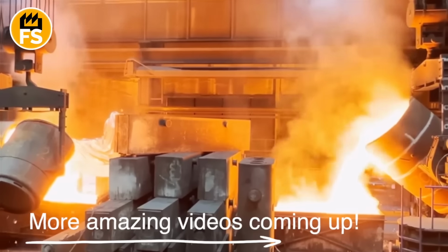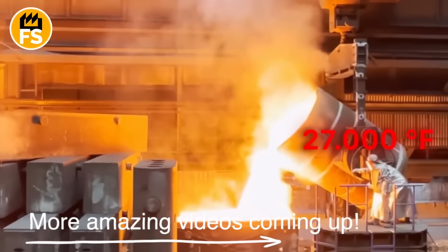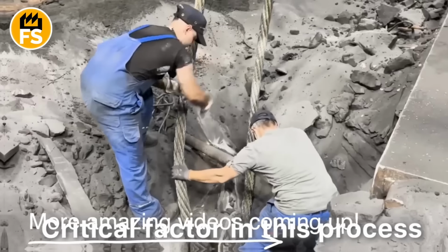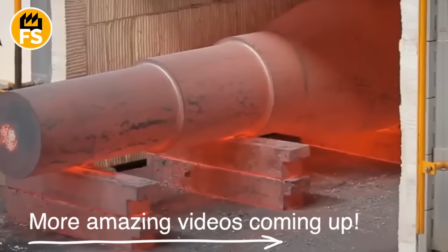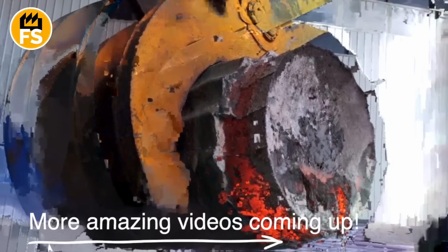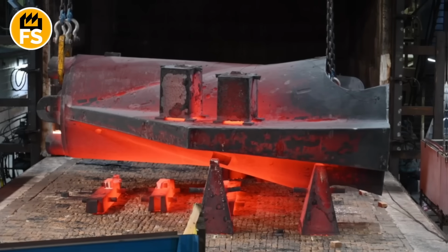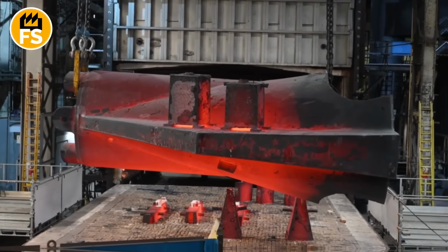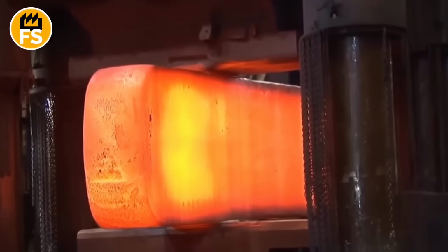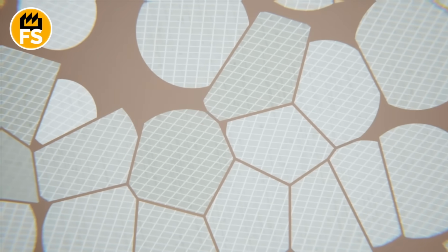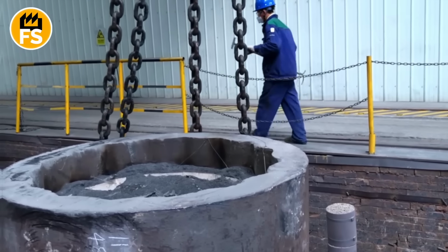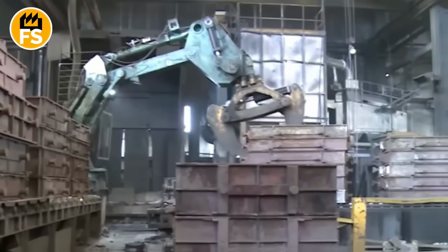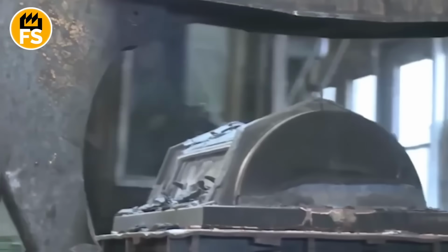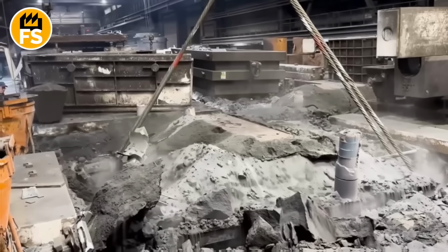Immediately after pouring the molten metal, which can exceed 2700 degrees Fahrenheit, time becomes the most critical factor in this process. Unlike small ingots that can cool quickly, a steel giant weighing hundreds of tons cannot be cooled rapidly. If cooling happens too fast, it leads to massive internal stresses, cracks, and structural defects because the outer layer solidifies while the steel inside is still liquid. To ensure uniformity of the crystalline structure, the 607-ton ingot was left to cool in the casting pit for 6 weeks. This is a controlled, incredibly slow process, during which the steel gradually solidifies, dropping to a temperature of around 2000 degrees.